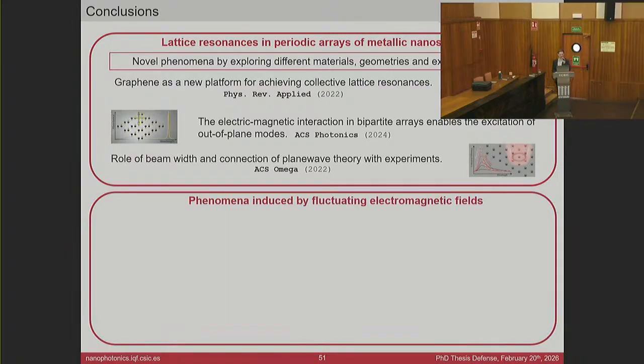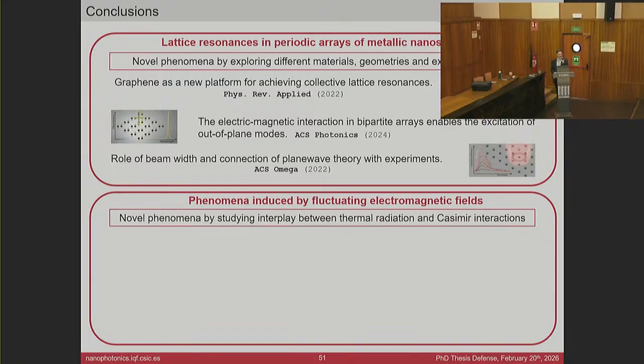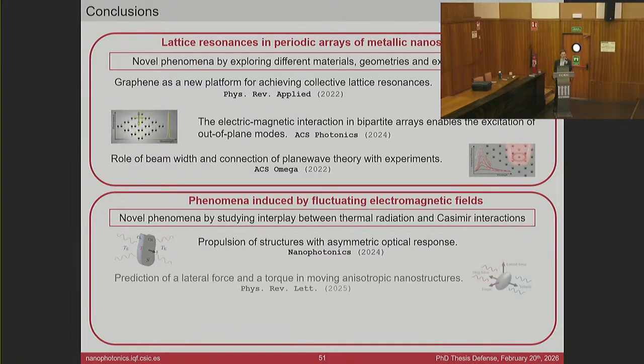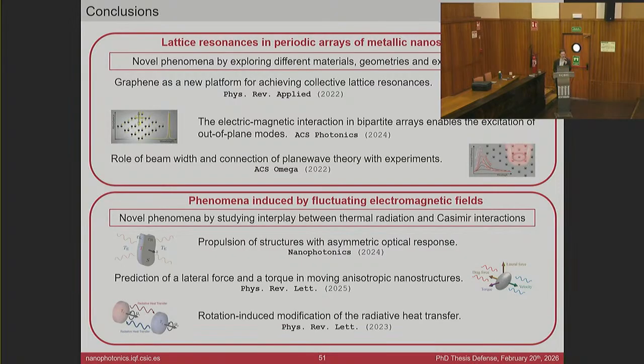In a different context, the context of phenomena induced by fluctuating electromagnetic fields, we have explored the interplay between thermal radiation and Casimir interactions to show the propulsion of structures with an asymmetrical optical response. We have predicted a lateral force and a torque in moving nanostructures if the nanostructure has an anisotropic profile, apart from the well-known drag force. And we have also explored how the heat transfer is modified in the interaction of two nanostructures because of the transfer of angular momentum between them.